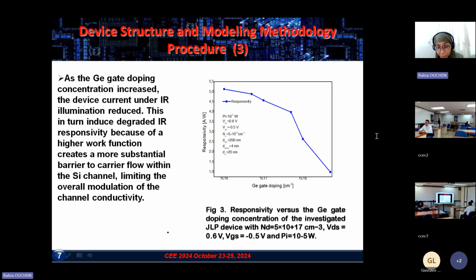Another curve presents the responsivity versus the germanium gate doping concentration of the investigated junctionless phototransistor device, with doping values and VGS, as shown. As the germanium gate doping concentration increased, the device current under IR illumination reduced, as shown in the curve. This in turn induced degraded IR responsivity, because a higher work function creates a more substantial barrier to carriers within the silicon channel, limiting the overall modulation of the channel conductivity.